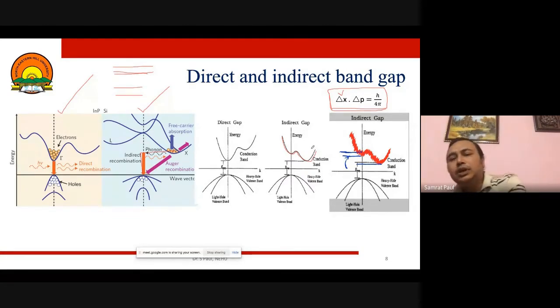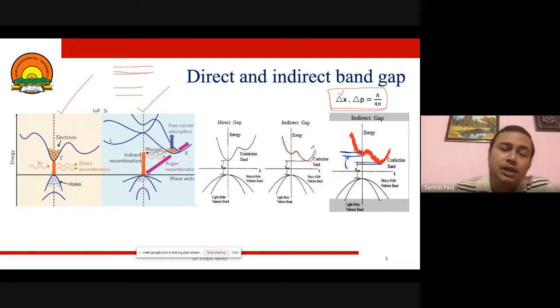But what happens if we take an amorphous material, or we incorporate some organic material or a glassy kind of material along with the structure? In these types of structures, if we go through any X direction or Y direction or Z direction, we see the regularity in the crystal structure changes very abruptly. In that case, the delta X becomes very big, meaning the uncertainty in the position becomes very big. And due to that, if we plot, we will not get a straight line. Instead, we'll get a blur kind of situation.